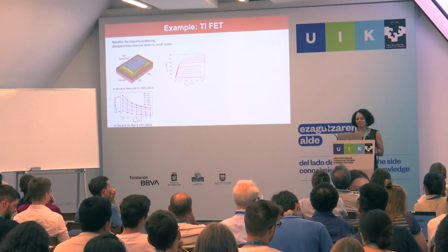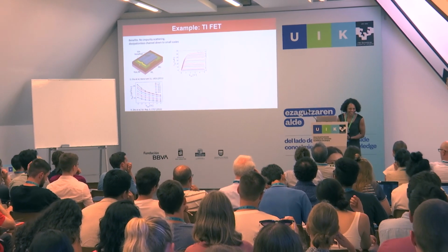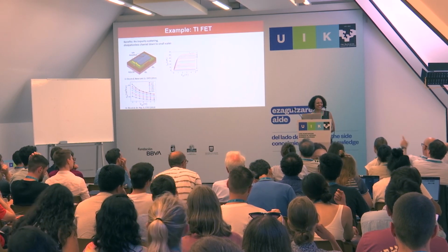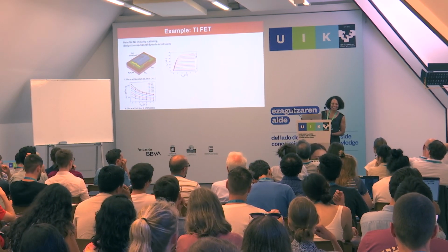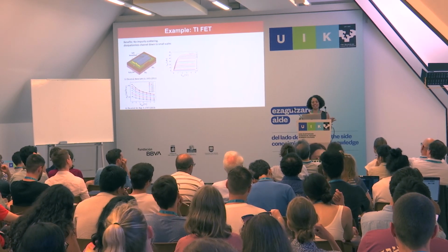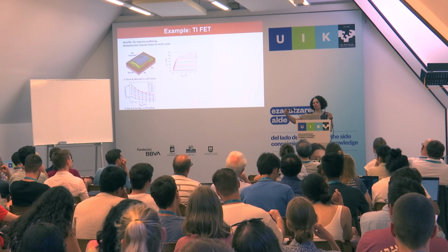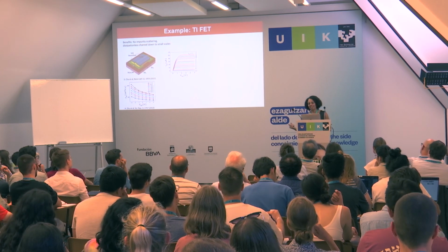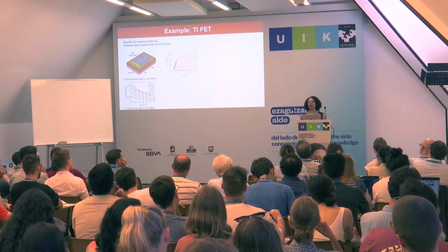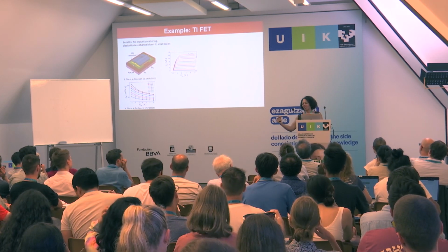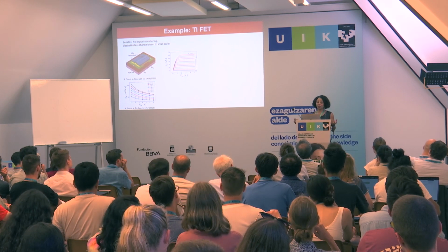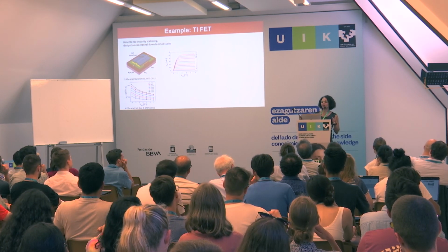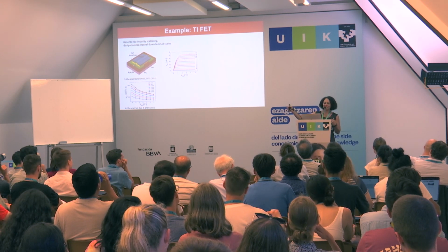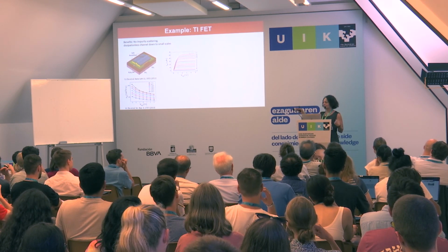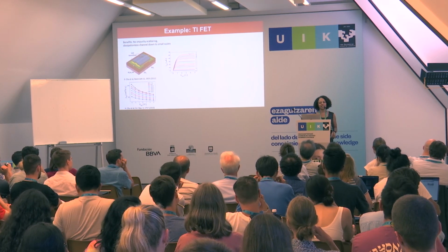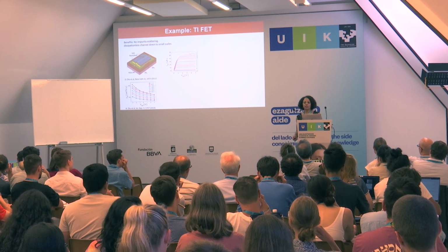Yeah, so I think I mentioned the transport was quasi-ballistic. You actually have phonon scattering in these. Right, so the situation is disappointing. Yeah, it is, and that's a problem. So in theory, there's lack of backscattering, right? But unfortunately, when you have a real wire, there's side scattering and angle scattering. There's all sorts of other scattering that can happen that's not just backscattering. So even in those nanowires that I showed you, where you saw the Aharonov-Bohm effect, it was quasi-ballistic. Maybe we saw Fabry-Perot oscillations. It was quasi-ballistic enough, at least on the 200 nanometer scale, that we could see those effects. But when you have a semiconductor with a reasonable channel length, you still get enough scattering that it kills the currents that you can carry, basically.